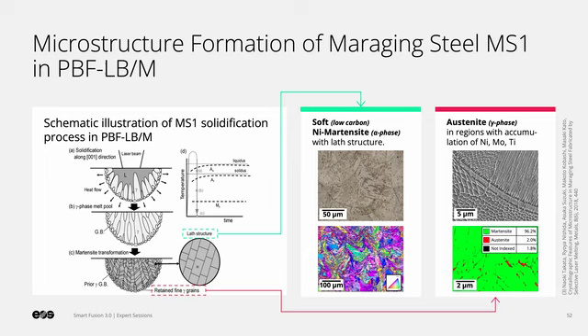Martensite has a lath-like structure which can be revealed either with etching, like we did here with V2A etchant, or using EBSD. In the maraging steel, a cellular and columnar solidification structure is formed due to the high cooling rates. Local accumulation of nickel, molybdenum, and titanium leads to the distinctly brighter appearance of cell boundaries. This also explains the presence of retained austenite, which is stabilized until room temperature due to the local differences in the element concentration. As-built austenite contents up to around 10% have been reported depending on the processing condition.